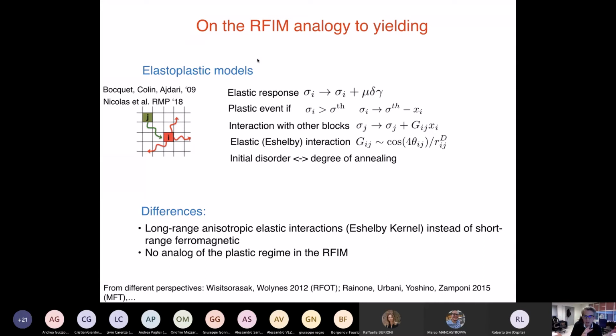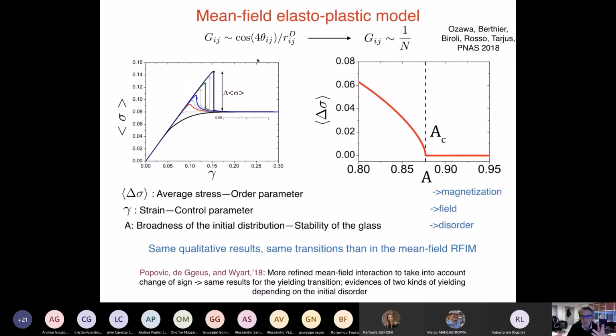All right, so there are similarities but also differences, and the idea is that we have to study this model to try to understand whether or not there is a relationship with what we have seen in the random field Ising model. So what we did is to study the elastoplastic model within mean field theory, and try to see whether we find a physics which is similar to the one of the random field Ising model. And the answer is yes. We studied this model like a cellular automaton, but we replaced the G_ij, which in 2 dimensions is the cosine of 4 theta divided by r to the d, r squared actually, by 1 over m. So it's a mean field version. And then if we do this, we can solve the model exactly.